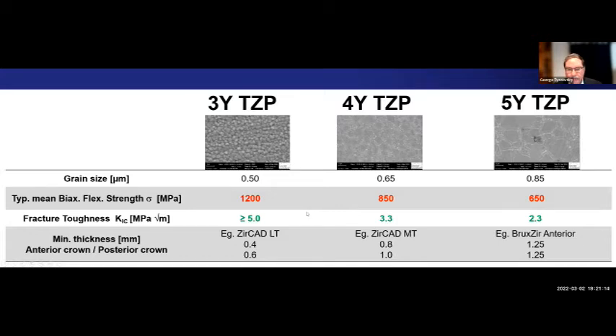We see the same comparisons with fracture toughness. Emax was about 2.75 for fracture toughness. Here we have a value of 5 on the 3Y material, so a very fracture resistant material. As soon as we start adding the cubic zirconia, we go to 3.3 and 2.3. So really, again, a balance of those properties.